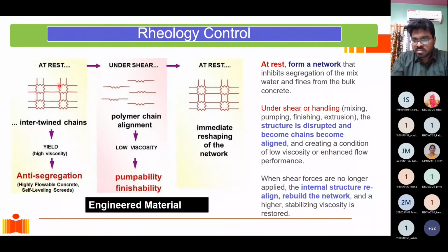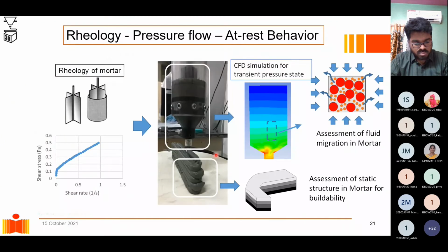So this is now what we are aiming to do. When the material is at rest, there is a structure that exists inside the concrete. And this structure basically consists of a network that is formed, which can resist shear. When I apply shear, the structure is disrupted. All the particles get aligned. And so I get a free flow which allows me pumpability and easy pumping. And then when I bring it to rest again, the structure develops inside, which is able to resist the applied shear stress. That means it keeps its shape. So this is what we're working on with rheology control.